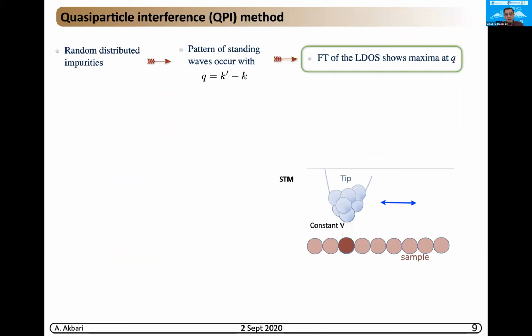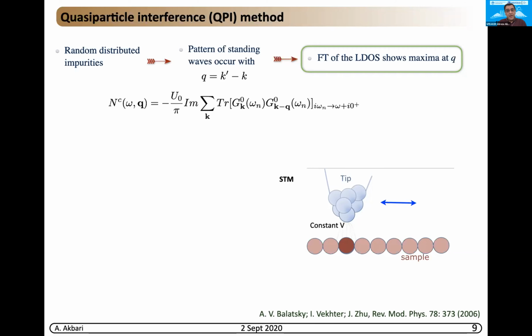For doing that, first I would like to say a few words about quasi-particle interference, which we know is an impurity-based technique. In the presence of impurity, the impurity can scatter the electrons, and as a result the scattered electron can interfere with the original electrons, and it produces a standing wave-like feature on the density of states on the surface of the sample, and this can be detected by STM. When you look at the Fourier transform of the STM result, it shows enhancement at a momentum vector Q. This can be represented even in the Born approximation with the convolution of the two propagators at incoming and outgoing momenta.